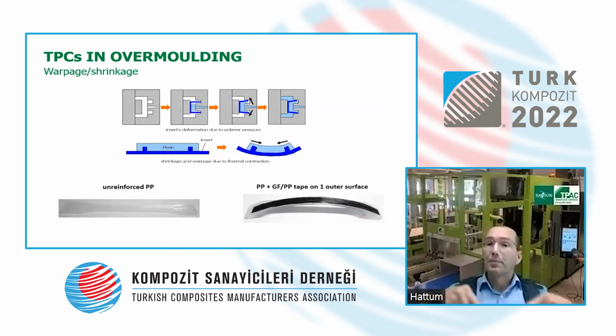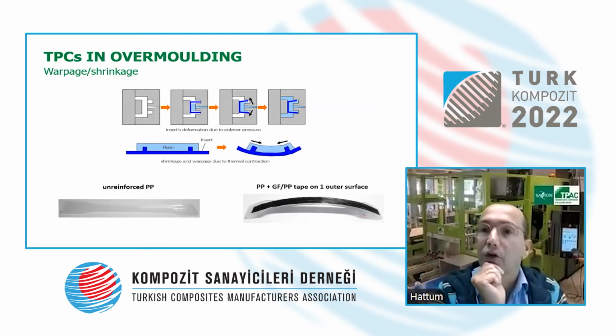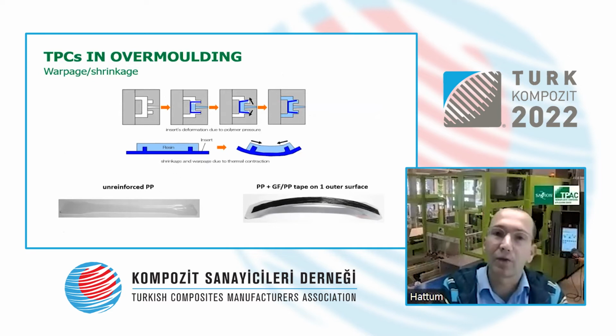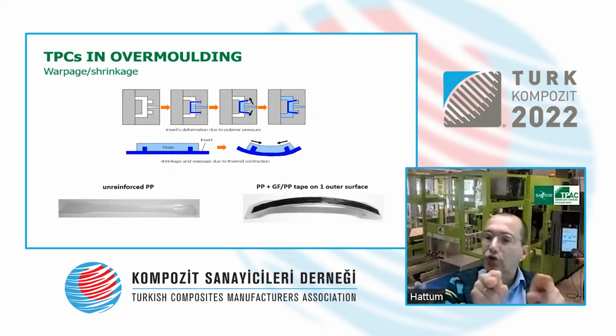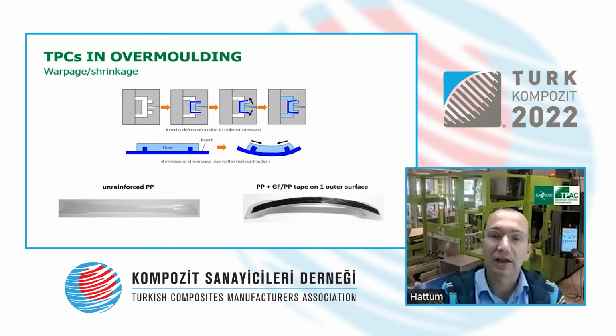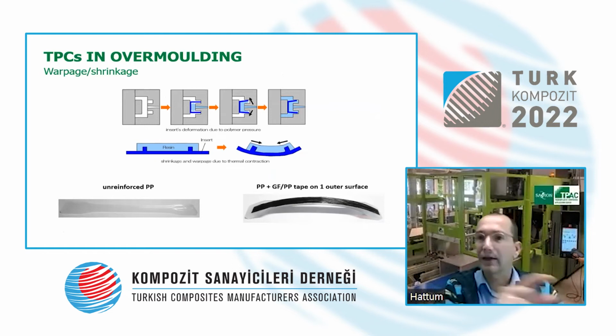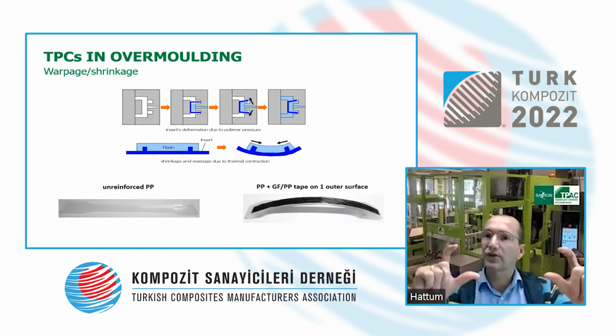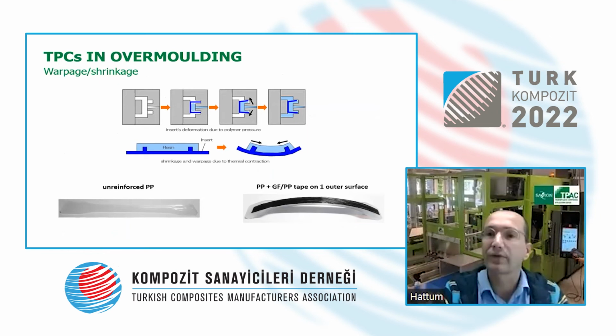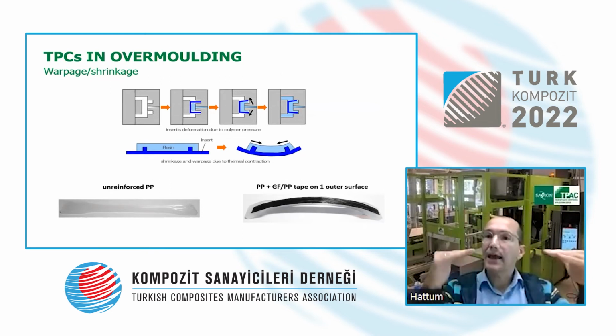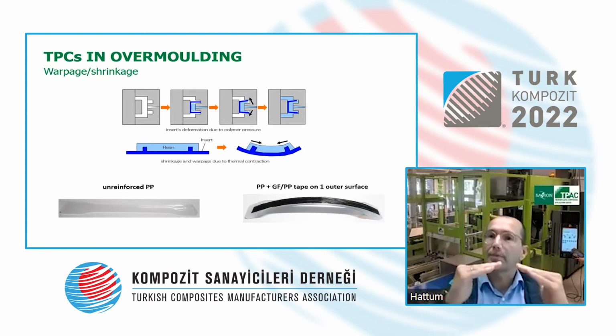The problem with locally reinforcing your parts to optimize the weight saving is that you introduce inhomogeneity into your part. So I show this with a very simple part. If you have a piece of plastic which is working fine, if you introduce composite, your stiffness and strength might increase with a factor of 10 or 15. However, if you do it in the wrong way, you can see it on the right-hand side, as the composite is not shrinking, but the plastic is shrinking a lot, you will create curvatures. And people in plastic land know this.